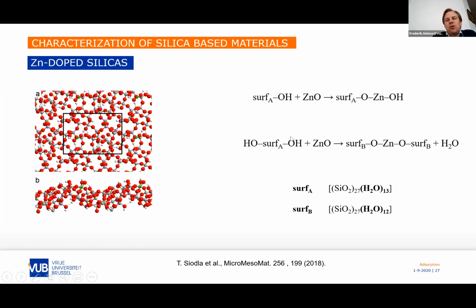So we grafted ZnO, the Zn2 plus, on our hydroxylated surface, and we make a link. We make a silicon oxygen zinc hydroxide site. We can do the same, but by making 2 links: silicon oxygen, zinc, oxygen silicon. Yeah?